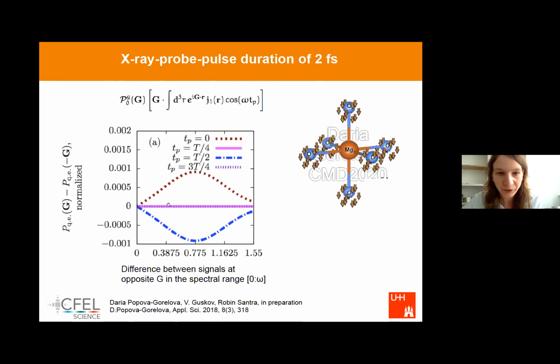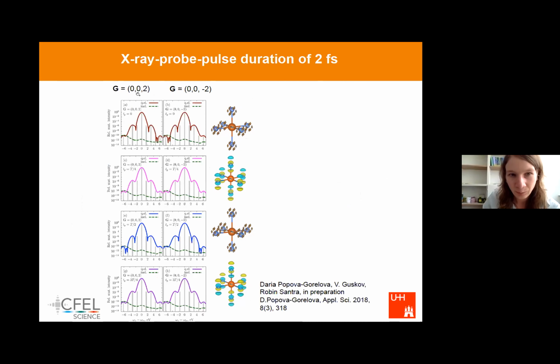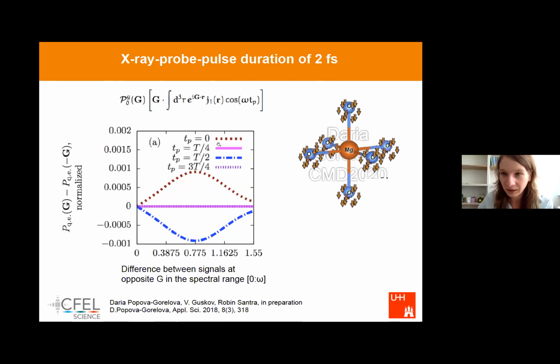Here, what I'm showing on this picture is the difference between the signal at positive G and negative G, depending on the phase. And we could show that this oscillation is proportional to the product between the Fourier transform of the field-free density of magnesium oxide and the Fourier transform of the electron current density. So in principle, when one knows the field-free density of the driven crystal, one can extract from this difference the Fourier transform of the microscopic electron current.